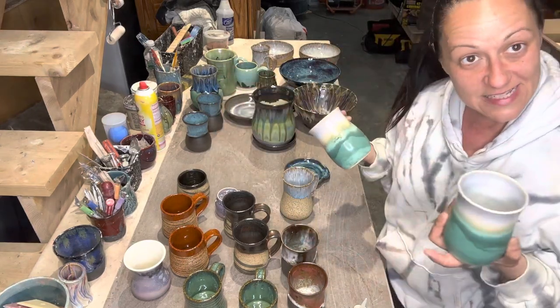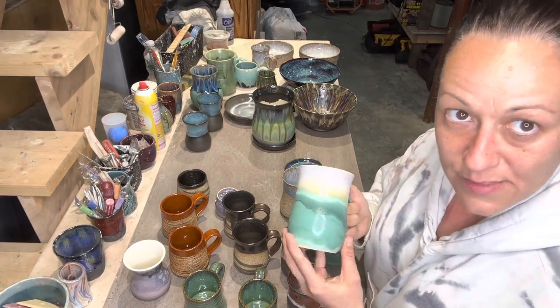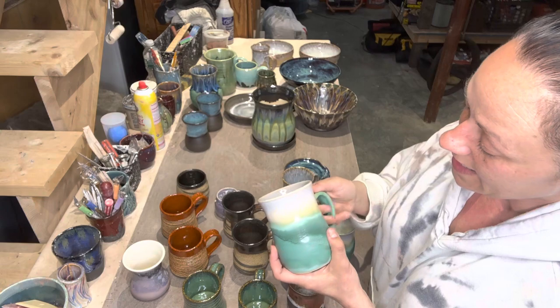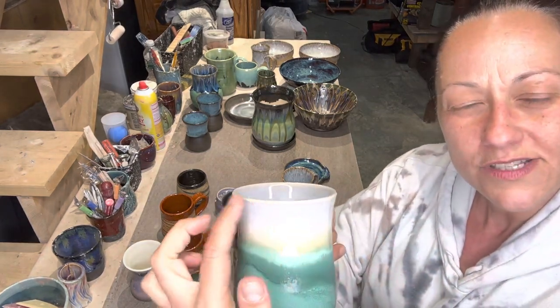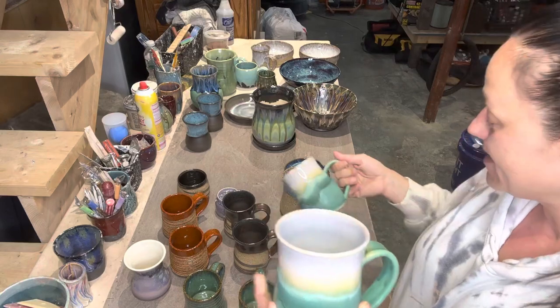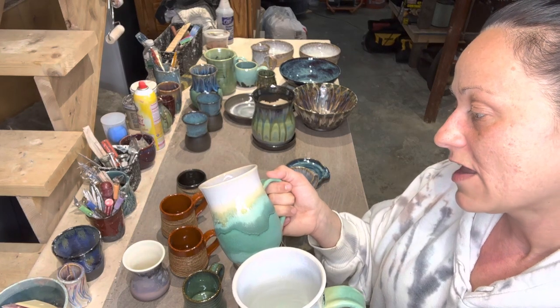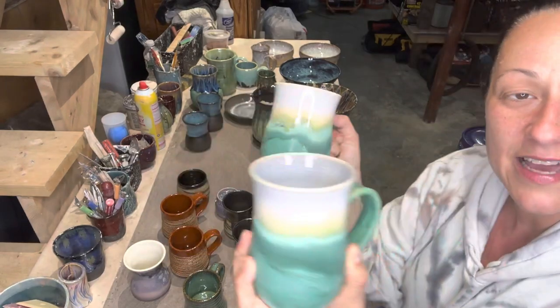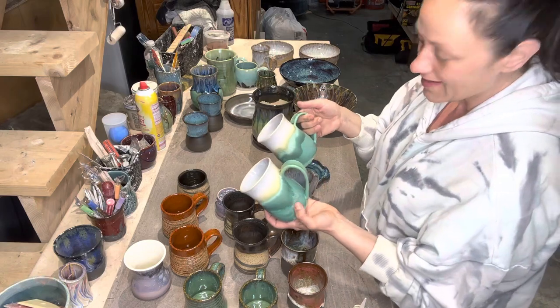These were a refire — I did an experiment. All I did was add a little bit more of this glaze because it had some bare spots with lighter coats that didn't go heavy enough. Also the soft white from Spectrum on the top had some little bubbles that get hard. So I put them back in with a tad more glaze, and when I refired them, the bubbles went away. I'm really happy with that — they were driving me nuts because you'd put your lips on it and it was sharp.